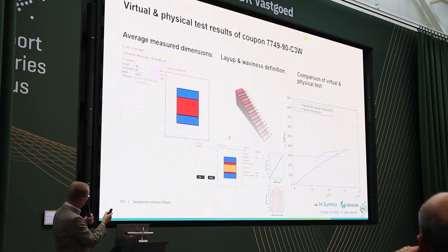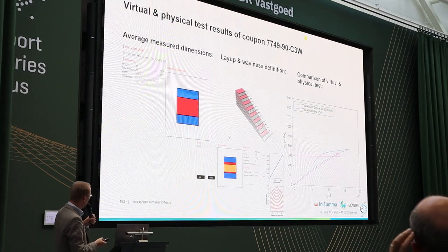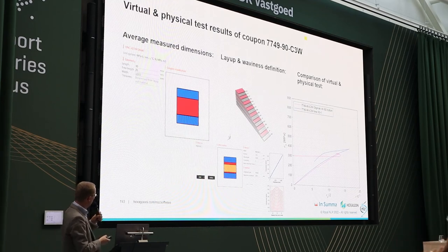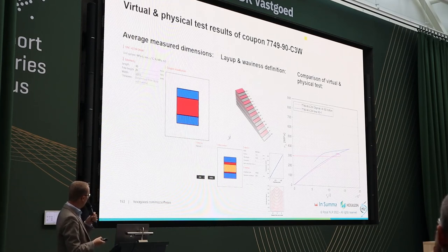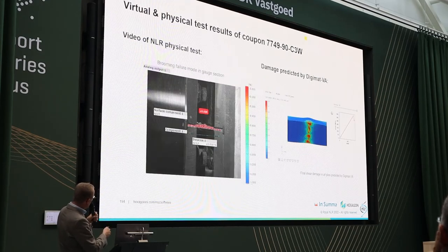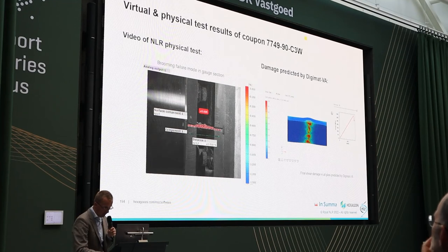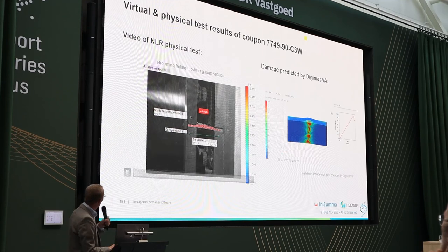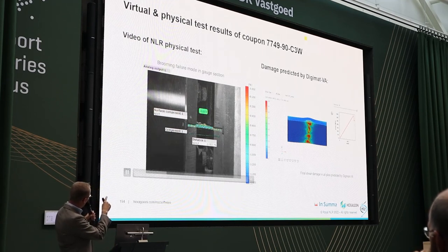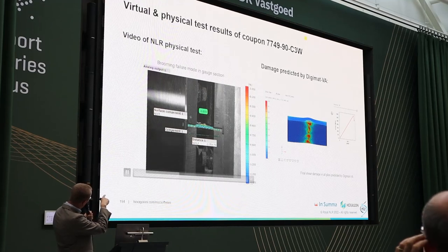And on the right, you see test versus simulation. Also here, stiffness is quite well predicted. There is some underprediction of the compressive strength, but also quite good. And here you see on the left the physical test. Let's see if that works. It starts moving, and on this coupon the strain on the side of the coupon was also measured. So you see when it bends in on the lower surface, there's compression.